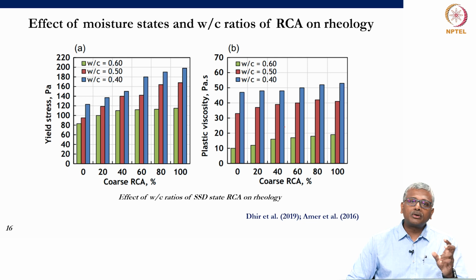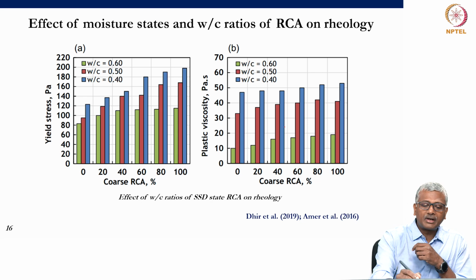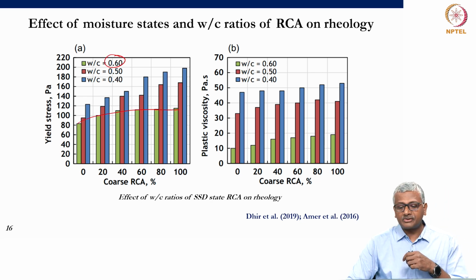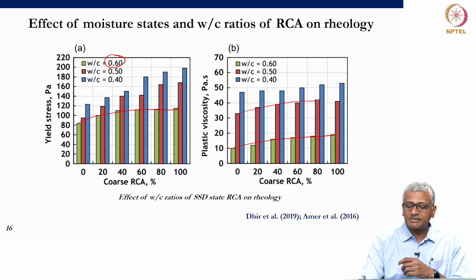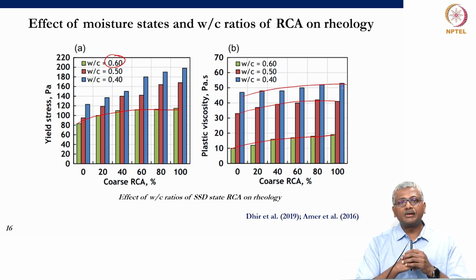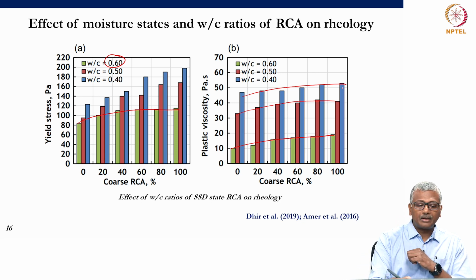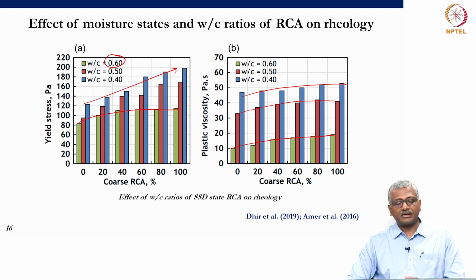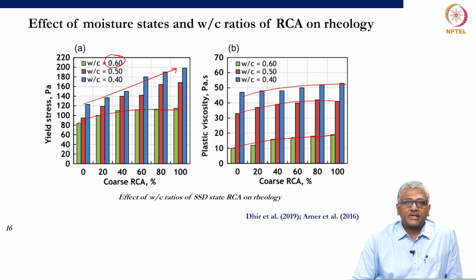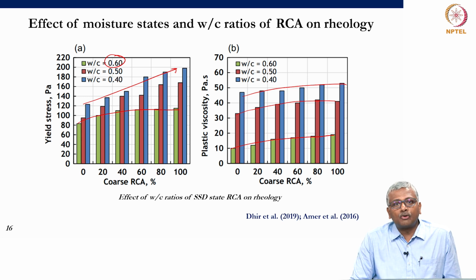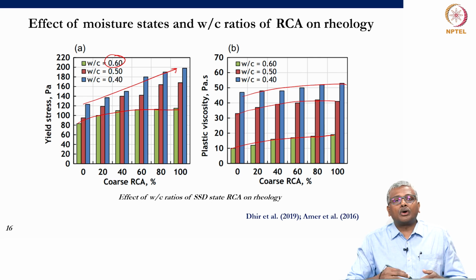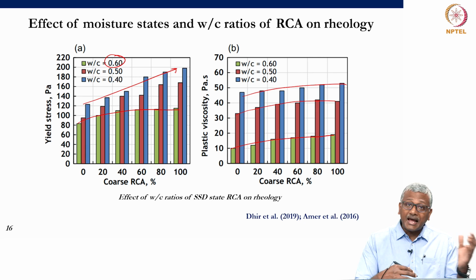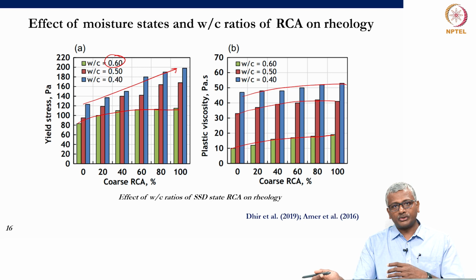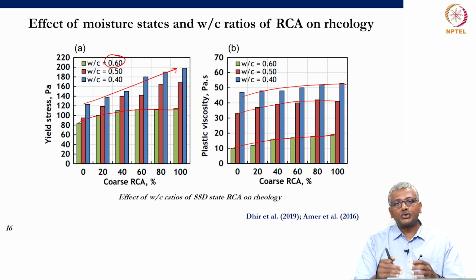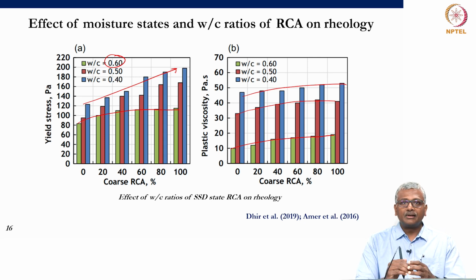Now, depending on the water to cement ratio, this behavior may or may not be very significant. For instance, when you go for a high water cement ratio, you can see that the increase in the yield stress and the increase in the plastic viscosity is not very significant. Okay. In fact, in terms of increasing water cement ratio, you see that the increase in plastic viscosity is still not very significant when you go for higher amount of coarse aggregate replacement by recycled concrete aggregate. But when you consider the yield stress, there is distinctly an effect at lower water cement ratio, there is distinctly an effect of increasing the yield stress when the extent of replacement of normal aggregate by recycled concrete aggregate goes up. Okay. So, if your concrete is already too wet, lot of water is present, then your effect on rheology is not as significant as when you start concrete designing with lower water binder ratios. So, again you need to consider the grade of the concrete for which you are designing with recycled concrete aggregate. The effect on rheology may not be consistent at high and low water cement ratios.